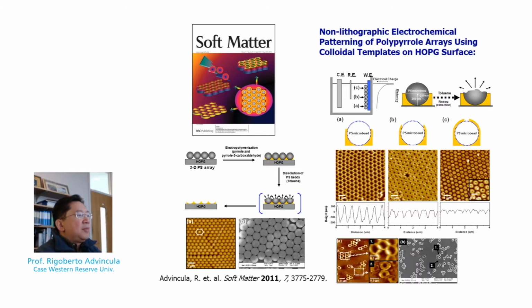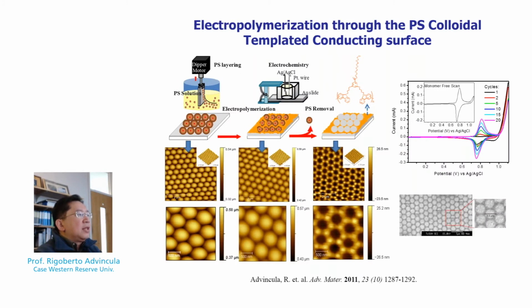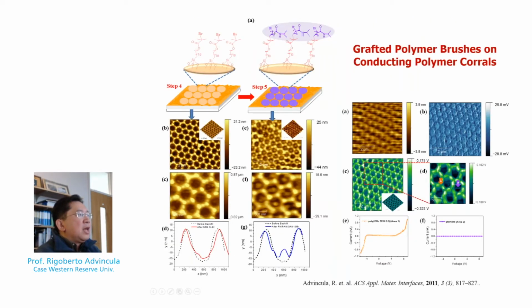And in fact, they can be harvested even as particles. So we have demonstrated that these conducting polymers can be grafted at the interface as shown here. However, since the holes of these arrays are basically exposed electrode surfaces, one can modify the surface to do polymer brush chemistry. And that's exactly what we've done in this work.